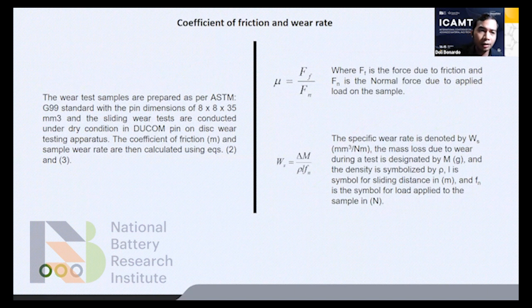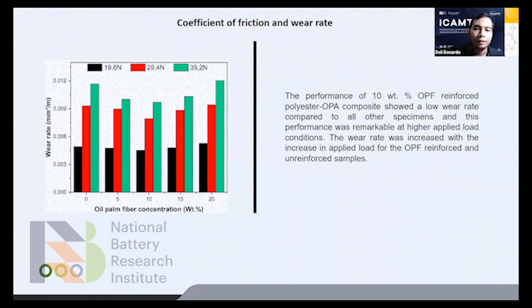And then the coefficient of friction and wear rate. The coefficient of friction and the sample wear and the wear rate were calculated using this equation. And the result: the performance of 10 weight percent OPF reinforced polyester composites shows a low wear rate compared to all other specimens. And this performance was remarkable at higher applied load conditions.